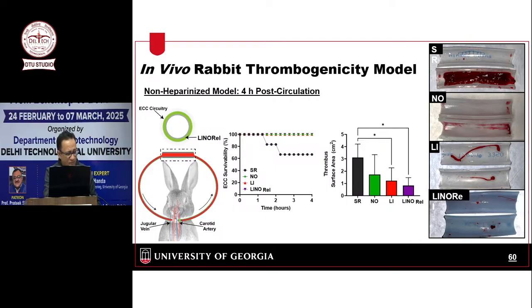By itself, if you see this graph, silicone rubber tubing, only 65-60% of the tubing survived. Like by 2 hours, some of the loops actually clotted. The flow rate went to 0. But NO, liquid infused NO surface, they all survived the full 4 hours at least. But then when we looked at the thrombus area, you can see how the thrombus area was. And when you see on the right side, you can see how there was so much thrombus in the top one, silicone rubber, and how NO, liquid infused, LiNORel, they all were nice. And liquid infused was maybe better than the other two.